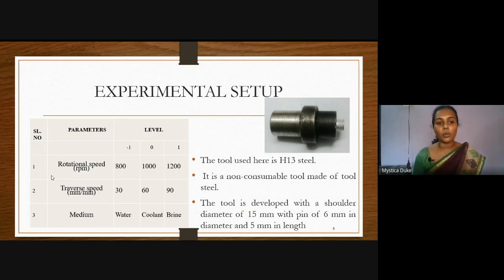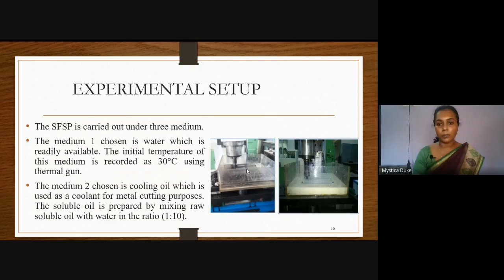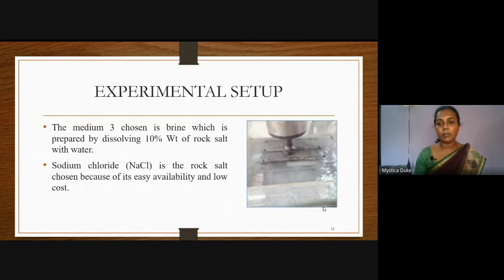And this is the parameter combination, which is very important for our study. We have taken 3 levels: the low level, middle level, and high level. We have varied the rotational speed, transverse speed, and the 3 different mediums presented here. This is the first medium, which is water. The initial temperature was recorded as 30 degrees Celsius. Here you can see the second medium, which is cooling oil. Cooling oil is nothing but the metal cutting oils which we normally use. We mixed it with water in the ratio of 1:10. Next, the third medium is the brine solution, which is 10% NaCl mixed with water.